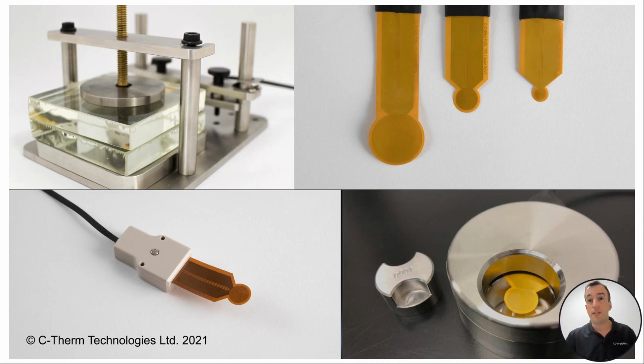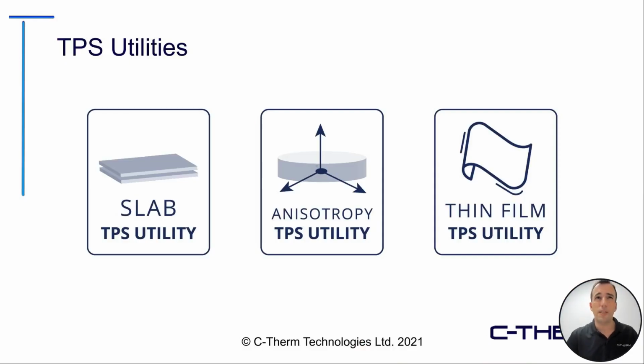Here we see some different accessories for the Flex TPS sensor, TPS sample clamp, top left, one of our higher temperature versions of these sensors. We have them available up to 500 plus degrees Celsius, but the standard ones are rated to about 80, 85 degrees Celsius. There are some different options available in terms of higher temperature, if it's so desired. Different sizes in the top right you see, and one of the powder test cells in the bottom right, all available with the Flex TPS sensor options. I mentioned those utilities earlier available with TPS. Slab allows you to test thinner sheets of material. There's the anisotropy test utility, and thin films, all available with these.